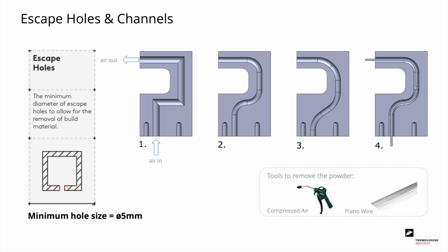Looking at the next design feature, we're having a look at escape holes and channels. Typically, you recommend a minimum hole size of about 5 millimeters. But it very much depends on the geometry. So if we take the part labeled with number 1, you would see this is going to be very difficult to clean. Typically you use compressed air or you use piano wire. And if you do that with these very sharp angles, it's going to be very difficult to empty it for powder. Going in to the second and the third option, you see it's much easier both to get the piano wire through it and to use compressed air to actually blow the powder out of it. The last option that we have included, labeled with number 4, is actually printing a solid wire up through it, and you can pull it out afterwards.